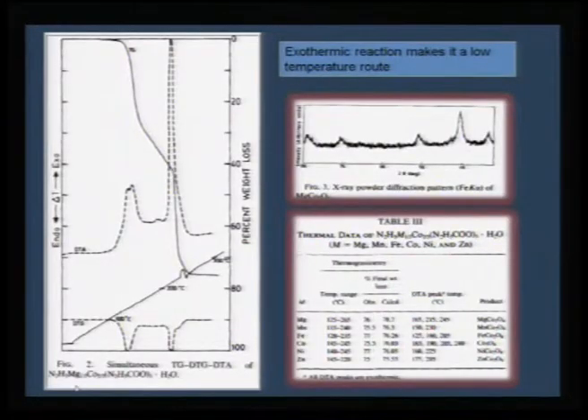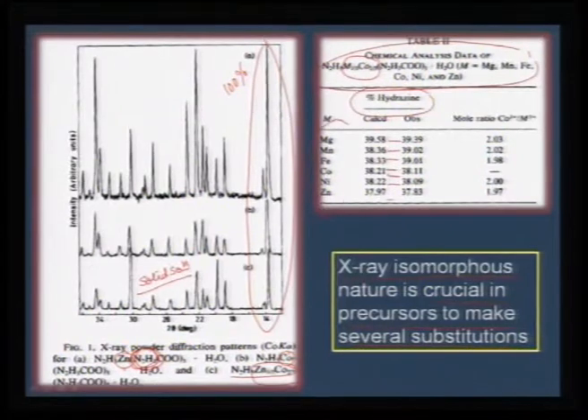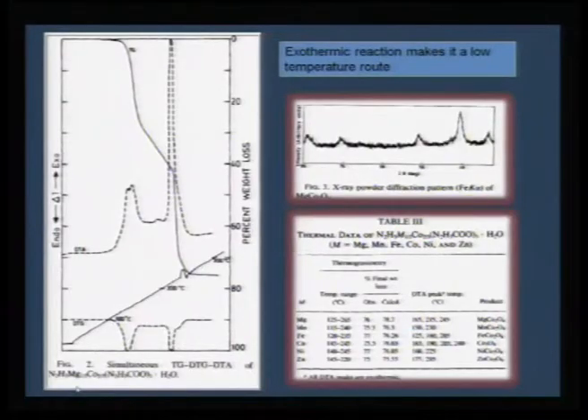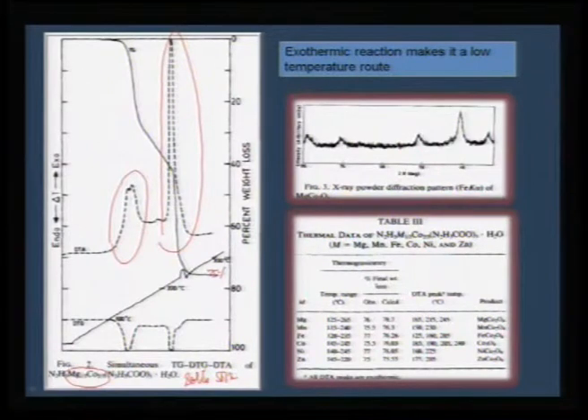Now, what is the power of this precursor? Can I use this for some application? Yes, because if I try to decompose this precursor, any precursor I have shown you here, and do a thermal analysis, thermogravimetry is actually very, very refined. For example, take the case of the magnesium cobalt solid solution. This is a solid solution, and if you run the TG-DTA, this is your TG pattern, which shows that there is a weight loss up to 75%. So, nearly 75% weight loss is there, and during this weight loss there are two things happening. One, there is a peak here, and then there is another peak which is forming here. Both incidentally are exothermic in nature.